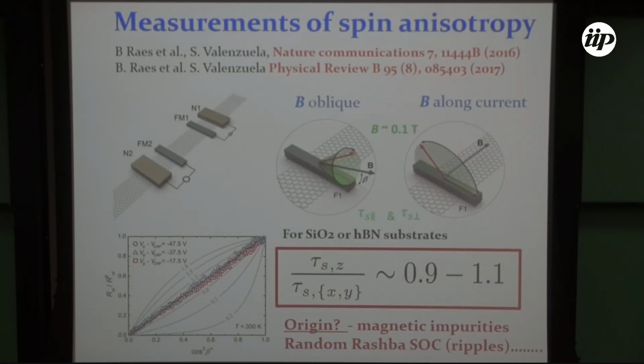However, it turns out that a method was developed, which will be presented by Roland, I think, in order to probe this spin transport anisotropy. And very careful work of Sergio's group for graphene on boron nitride and graphene on silicon oxide did not lead to 1/2, but just 1. So isotropic spin relaxation time, which is incompatible with Dyakonov-Perel and strong disorder.